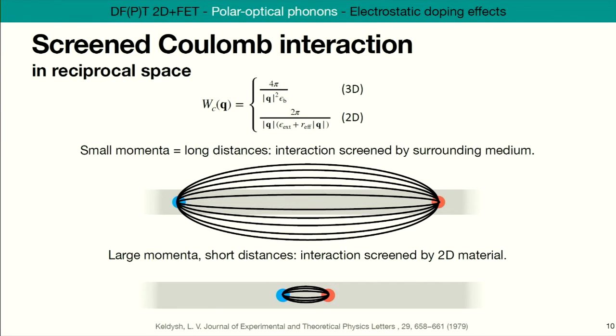The bare Coulomb kernel, as you might know, in reciprocal space is 1 over Q squared in 3D, the classic one. In 2D, it's 1 over Q. And then you also have a difference in the dielectric functions here. In 3D, you can usually get by just dividing by a constant, the bulk dielectric constant of the material. But in 2D, it's quite different. It's linear, so it has a constant term and a linear term. This is because screening inherently depends on the wavelength or the distances in 2D.